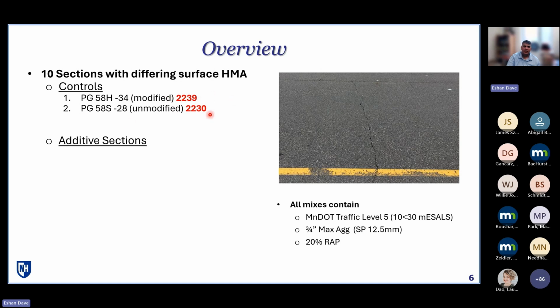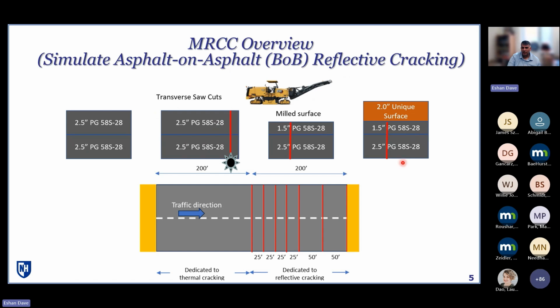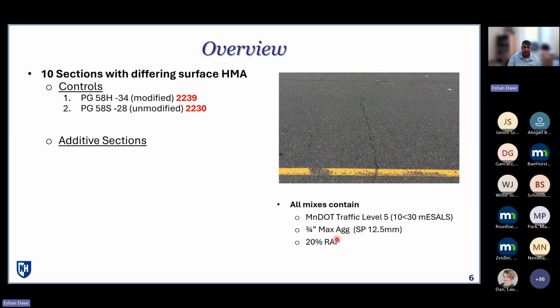Keep in mind that this 20 to 30 mix is also the mix that forms this bottom 4 inches on all of these cells. So that's your standard base mix there. Then we have the additive sections, and the first two comparative sections have aramid fiber. So they are made with that modified binder together with aramid fiber, two different manufacturers that you'll see on next slide. And really that's the main difference there with cells 33 and 34.